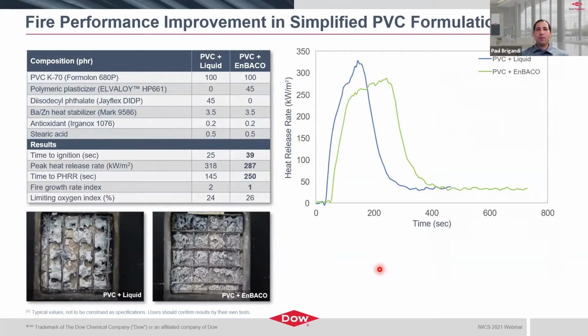Now, we can couple this to the fire performance, which is really a critical aspect of these materials, particularly the plenum rated cable. In this case, we're looking at a very simplified PVC formulation, and we're doing that strictly to understand the benefits, if there are any, of the polymer modifier on the composition as it relates to fire performance. So here we're looking at a straight comparison of PVC plus liquid and PVC plus one of the polymeric plasticizers. We have added in this case diisodecylphthalate, so DIDP here, at an equivalent loading as we have the polymeric. Just some other heat stabilizers, antioxidants, just for some slight stabilization.